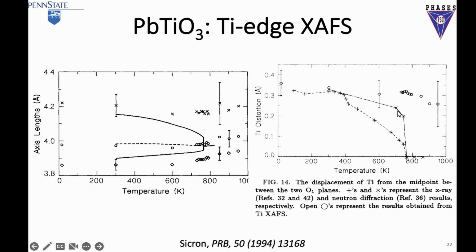So it shows that at the transition temperature they go to 0. That's right, no polarization. However, if you look at the individual titanium cell, the polarization stays at all temperatures. It never disappears. So that means that the Landau theory is macroscopically correct, but microscopically incorrect. It did not represent reality, what the atom does.